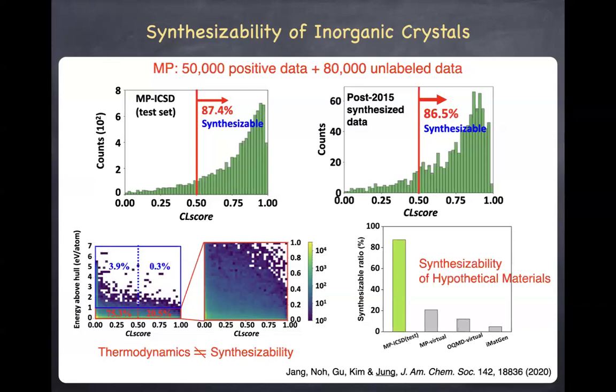And on the lower right corner, I am showing you the application of this synthesizability machine learning model towards a few hypothetical databases, MP virtual and OQMD virtual, and you see that about 10 to 20% of them are predicted to be synthesizable. And that means that for these hypothetical inorganic compound databases, the remaining 80 to 90% of them may be hard to synthesize, even though some of them may be recognized as having promising properties. So having this kind of filter in your screening pipeline, one might be able to save some time and cost for experimental attempts.